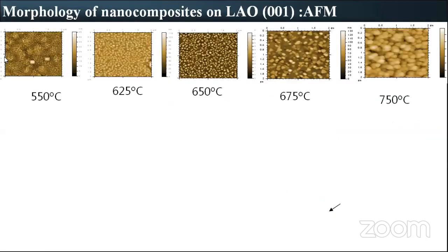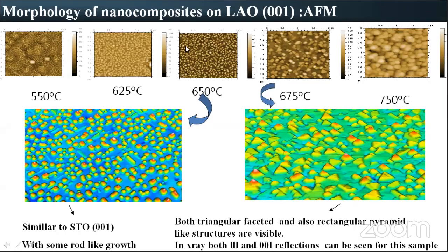Okay, so this is again the AFM images for films grown at different temperatures. At our optimal growth temperature, you can see clear 001 oriented spinel on a very clean matrix. But if you increase the temperature, there are some 111 oriented rods also. I'm not going into the details of the growth parameters. So what will happen if you change the strain?